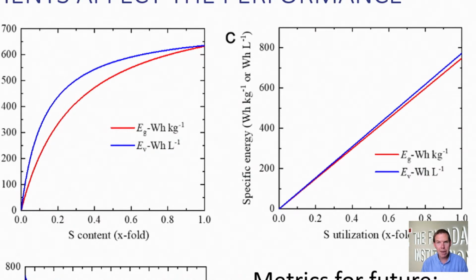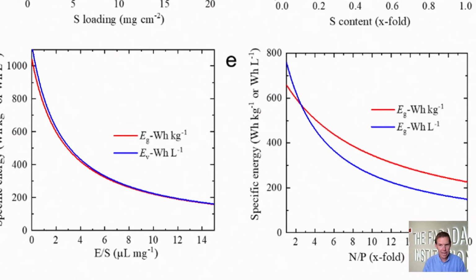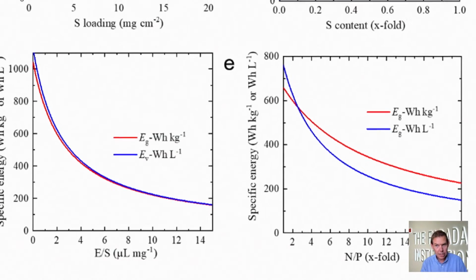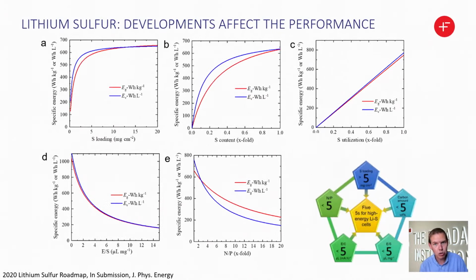And so there was a recent paper which was published by the Texas A&M group, who have done a lot of thought leadership in the area, where they were targeting the 5 5s for high energy lithium-sulfur cells. And this gives us a really ambitious target to try and develop both electrodes, electrolytes, and indeed whole battery systems to be able to begin to tackle and develop lithium-sulfur batteries with really enhanced watt-hours per kilogram in order to become a challenger to the incumbent lithium-ion battery technology.